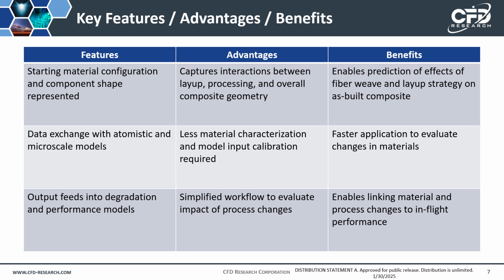By modeling the steps of the process in woven fiber unit cells, in addition to component scale models with unit cell average properties, our approach lets us directly predict how the fiber weave and the way the layers are aligned affects any residual porosity or other as-built defects. This also gives us a direct path to more mature models developed under other efforts that predict not only the as-built composite stress-strain response, but also how it accumulates damage under loads in its strength. The overall toolchain allows us to link starting material and process condition changes to how the component made from the composite performs in flight.